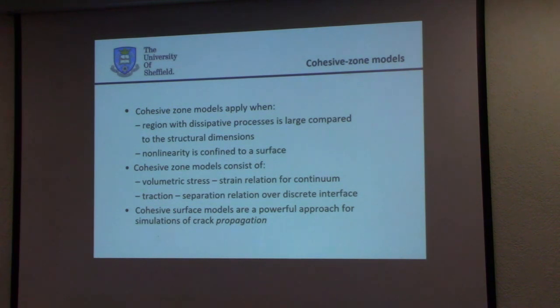Now, there are lots of cases where you can use linear elastic fracture mechanics, but there are also some cases where you can't. You can use linear elastic fracture mechanics primarily if fracture is the main source of energy dissipation. Usually you have some inelastic processes around the crack tip. But if the energy dissipation there is small compared to the energy dissipation due to fracture, then this can be disregarded.